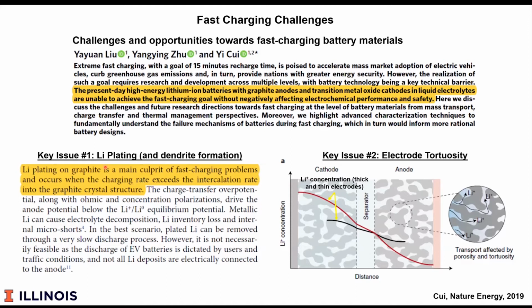And because the driving force for lithium intercalation into graphite is low, it is very difficult to drive it quickly. If you apply a large overpotential, you get below the Li+/Li0 equilibrium potential, which means metal lithium forms.